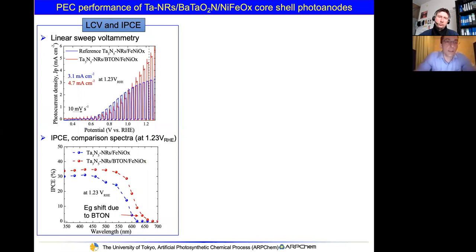Okay, and then this is again the IV characteristic of both materials. So this blue one is the tantalum nitride nanorod, and the red one is the core-shell nanostructure. So you can see here we have good enhancement. But what is very interesting is the band gap shift due to the barium tantalum oxynitride. So this is exactly at 1.9 electron volt. So this is the third confirmation that we realized this structure.